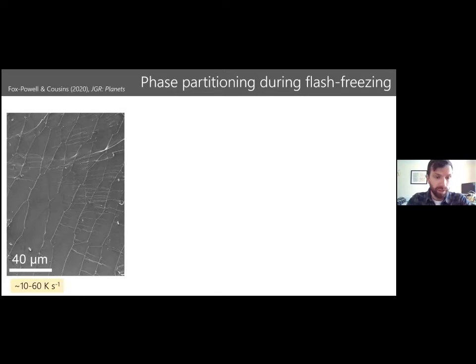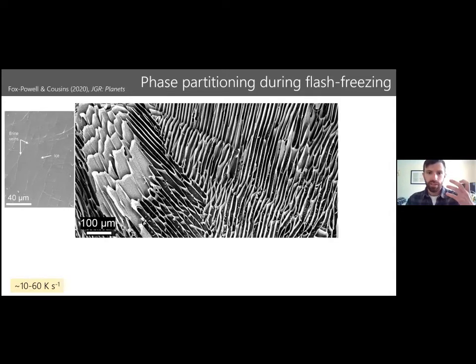So even at these really rapid cooling rates, we have partitioning. We have the formation of this brine vein network, which I mentioned earlier, that is known to form through freezing. The dark material here is ice, and the light material is this solute-rich brine that's been excluded to ice grain boundaries. What we did is sublimate away some of the ice, and that reveals the structure of this brine vein network in a lot more detail. We were able to calculate that it occupies about 5% of the droplet volume. So that means the solutes in there have been concentrated to about 20 times their original concentration and are now oversaturated with respect to several minerals that are expected to form in the system.